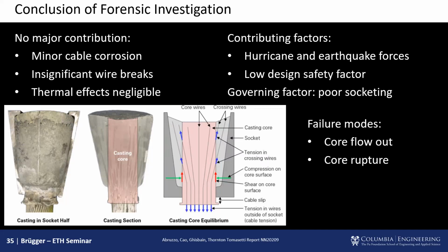And what happened was that this column was slowly extruded out of the socket and then pulling with it or fracturing the wires on the outside. That's why we saw that preferential slip of those outer wires, even in the sockets that had not failed, because they were essentially, without fail, all poorly socketed.